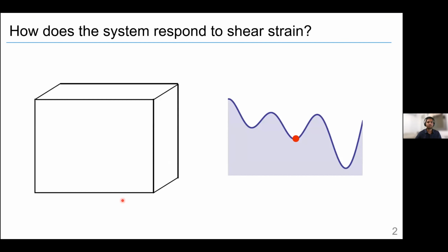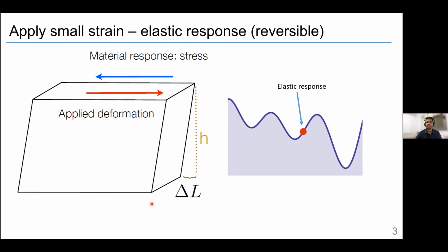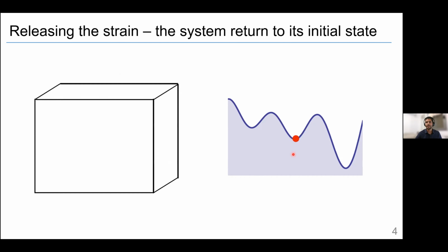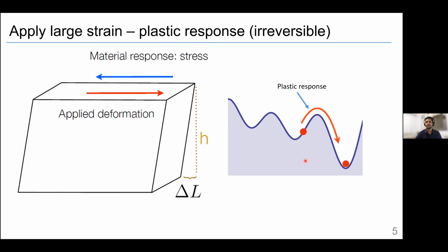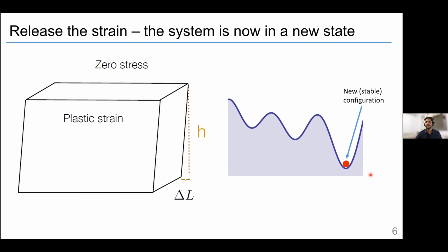Okay, so how does the system respond to shear strain? So we apply a strain. If it is small enough, the response is elastic. So we are around a minimum of the energy landscape, and we shift it just a little bit. So if we reverse it, the system returns to the original configuration. But if the strain is large enough, the system will go plastic and transform to a new minimum of the energy landscape. When we release the strain, we remain in this region and will not be in the same configuration.